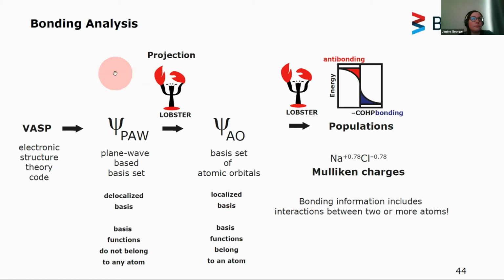So this bonding analysis, however, is not a very simple task. We have to do several steps because we need to use two programs. And therefore, automatizing these kinds of processes was really necessary to get large amounts of data. We start with, in this case, a DFT computation, a VASP computation. We compute the wave function in a plane wave-based basis set in this case. And then you have a delocalized information. So you cannot really get any information about the chemistry of the interactions between atoms. And to get this then, we need the program LOBSTER that projects these plane wave-based bases to an atomic orbital-based basis.